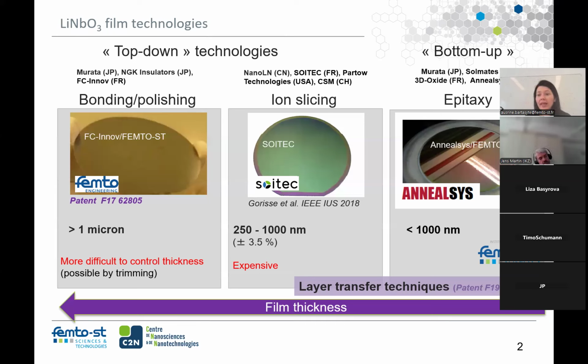And of course, when you do heteroepitaxy, your substrate has different thermal expansion. Then you get a limitation of the thickness because the film may be twinned or cracked and so on. So basically, if you do homoepitaxy, then your thickness is not limited, but then you have less interest in doing it. And then epitaxy stays a little bit on the side of all these methods and is considered as less mature, let's say. And me personally, I started to work on thin films when everybody abandoned them. So it was a very amazing time, let's say, when everybody didn't believe anymore that you can make films by growth, and you're trying to convince them that it's probably still possible.